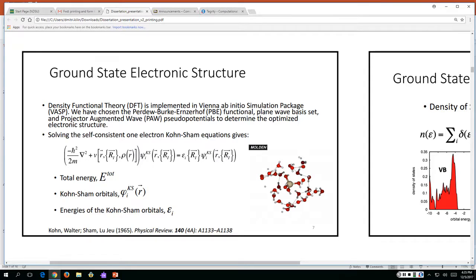One of the results of combining the absorption calculations and our molecular dynamic simulations is that we can look at a molecular dynamic photoluminescence result. What I'm showing on the screen are the fluctuations of Kohn-Sham orbital energies, which were the solution to our initial optimization. If we pick the HOMO and the LUMO as the two orbitals in which we're interested for the transition, we can calculate the absorption, the oscillator strength and the absorption value at each instant of time. Then if we look at a total summation or time average along the entirety of the trajectory, we're able to get some type of emission spectra taking into account the nuclear motion of the system. And so this can solve for issues seen in line widths of calculated spectra that are too thin, and account for the inhomogeneous broadening.